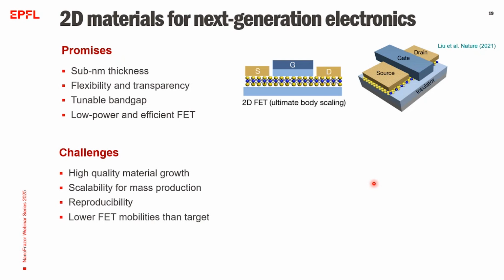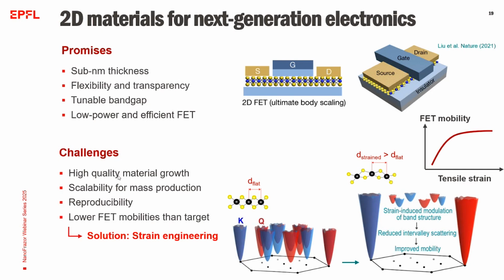These challenges include scalable material growth, reproducibility, achieving high quality and uniformity in grown material, particularly in terms of the mobilities. And similar to successful implementation in commercialized silicon transistors, silicon MOSFETs, strain engineering has demonstrated its effectiveness in enhancing 2D semiconductor mobility as well, by simply reducing the scattering within the material. And this leads to significantly improved mobilities under tensile strain, making 2D materials more attractive for nanoelectronics applications.